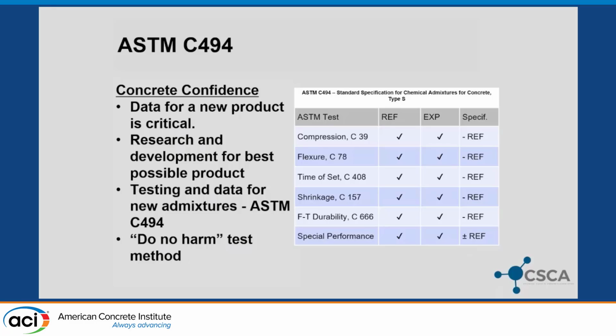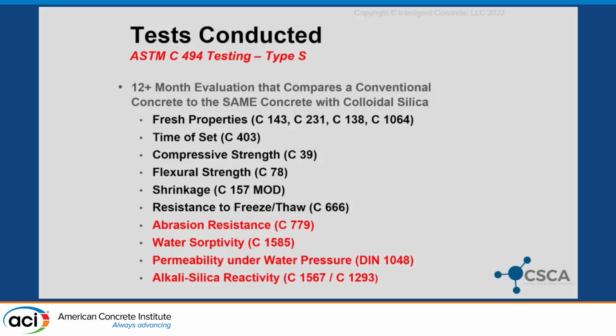But creating an environment where the microbes don't start flourishing, like I said, anybody can get strength, but having that special of an admixture, nobody minds, or most folks don't mind, if you do reduce strength a skosh. Or a bit. So as you can see, compressive strength, flexural strength, time of set, shrinkage, freeze-thaw durability, and then of course your special performance. And with all of these, you are allowed a minus or a plus from the reference, but as it turns out with your type S, you're definitely allowed a minus over the reference.